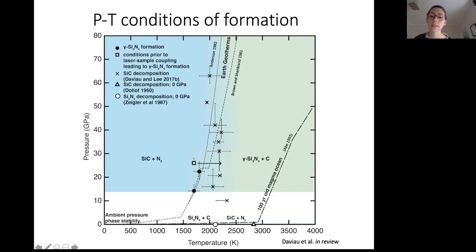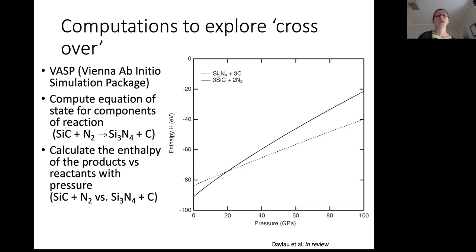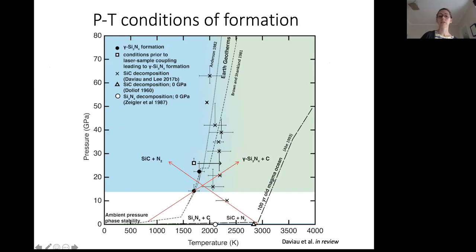Right, and so if you compare this to planetary conditions, looking at Earth geotherms, we're right around where the Earth's mantle sits. But what's interesting is that if you look at ambient pressure data, the opposite phase stability is present, so that at high temperatures, silicon carbide and nitrogen is the stable phase at low pressures, which is opposite of what we see when pressure is increased. We see that silicon nitride and carbon is the stable high temperature phase. Right, so we did some computations to explore this crossover, which I have highlighted in the red arrows here.